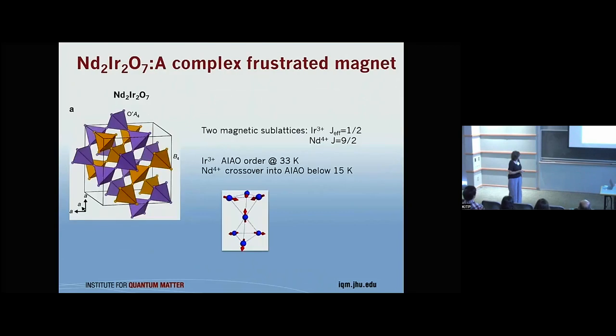One thing here is that iridium is a very strong absorber of neutrons. Half of the experimental talks here are on neutron scattering, and I think the reason there was space for us to do a lot here is that neutron scattering is very challenging in this system due to absorption of neutrons. The ground state was known from neutron scattering at very low temperatures, at 2K, where people looked at the neodymium sublattice and then deduced what's going on with the iridium sublattice from the magnetic moment. But probing the iridium sublattice directly is a challenge.